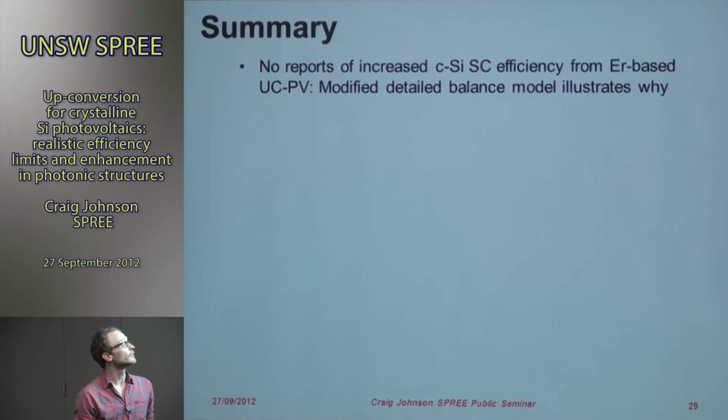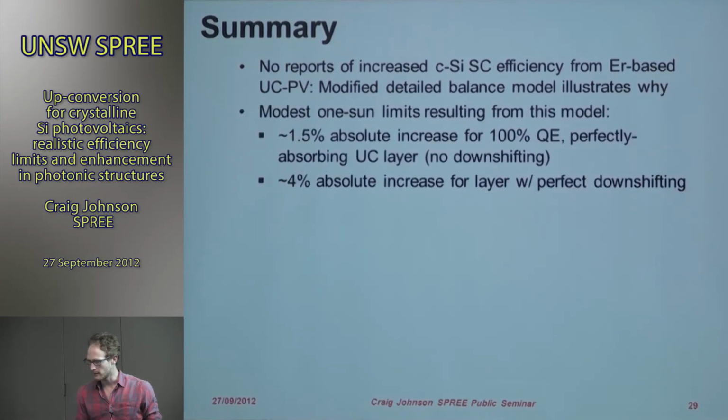So to summarize all that, there have been no reports of increased crystalline silicon efficiency from erbium-based upconversion, not in any case, even though there are quite a few experiments that have been looking into this. But the modified detailed balance really shows why. The limits from this are really quite modest.